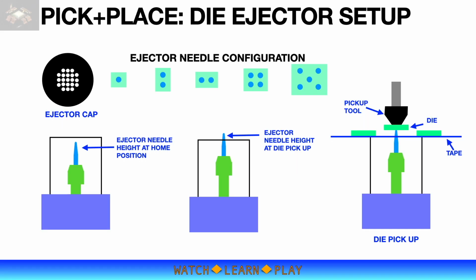Let's now talk about die ejector setup. Again, die comes in different sizes. A small die requires a single needle, but a larger die must use 2 or more needles and must be configured according to die shape. Ejector setup is critical to make sure that the die is picked up properly without any damage and misrotation. A damaged die, like chipped or cracked, must be rejected as this poses a significant reliability risk.